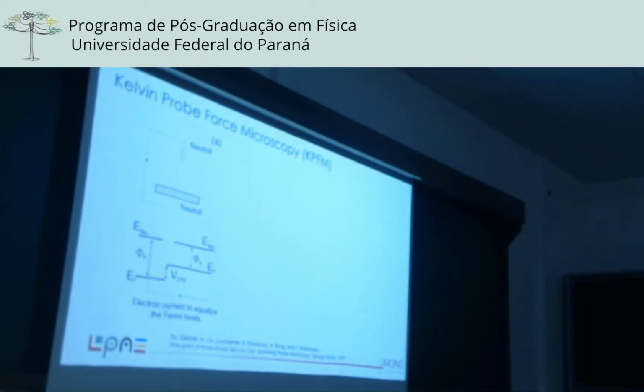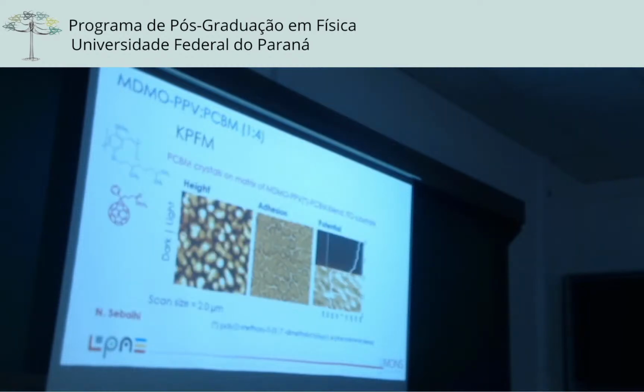You can also make some KPFM, Kelvin probe force microscopy, because some people are measuring not the current, but the voltage out of the solar cells. We have the same situation here. We have the topography, the adhesion, the potential, and you see a big difference in the potential when you are switching the light.